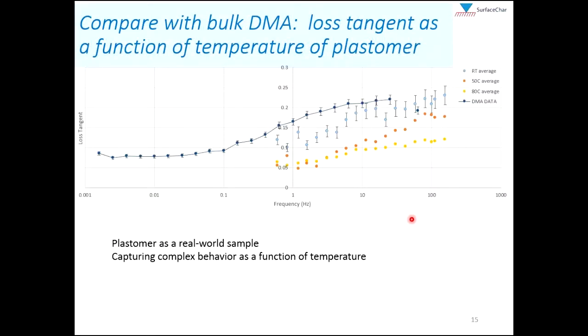Another example of a more real-world sample, called a plastomer, where we looked at the loss tangent as a function of frequency and temperature now. These dark blue dots that are connected are the bulk room temperature DMA data for the loss tangent of the plastomer. The light blue is the room temperature AFM-nDMA data. Again, it's a little bit low on this plastomer. And then we raised the temperature. The orange points are the AFM-nDMA at 50 degrees C, and the yellow points are the AFM-nDMA at 80 degrees C. We can see a plateauing of the loss tangent as we raise the temperature, as this plastomer is approaching very close to its thermal transition.